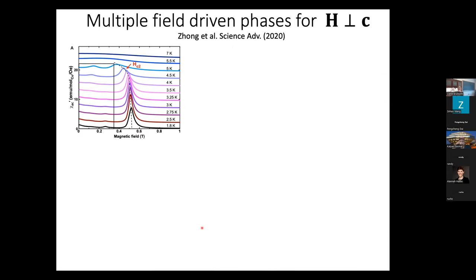And so this is actually what we want to be able to have Kitaev interactions. And so this is part of the reason that cobalt is a good choice, or a possible choice, to try to realize Kitaev-type physics. Now, to say a few words about the phase diagram of this material, shown here is the AC susceptibility as a function of applied DC field at various different temperatures. And you can see that if I go to the lowest temperature here, 1.8 Kelvin, then there is a phase transition at around 0.55 Tesla. We'll return to that phase transition quite a bit, actually.